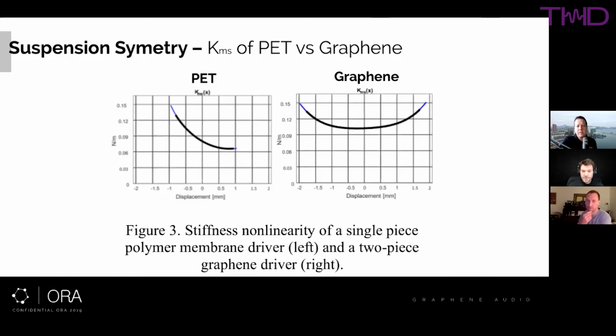They look like mountain ranges, the suspensions there, with peaks and dips and strange geometries in the suspension itself. They've got a technique to injection mold or vacuum form the surround directly onto the material. Yeah, it's injection molded, and they're guys I know from Taiwan. They're using optical grade tooling, so the tooling's the expensive part, but the ability to be precise down to 35 microns in the surround, and also design it in 3 dimensions, and then you're bonding the diaphragm dome to the basket ring, whatever the outside part, all in one shot.